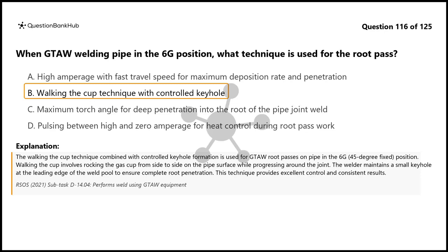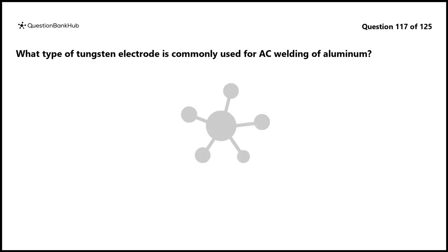The welder maintains a small keyhole at the leading edge of the weld pool to ensure complete root penetration. This technique provides excellent control and consistent results. Question 117. What type of tungsten electrode is commonly used for AC welding of aluminum?